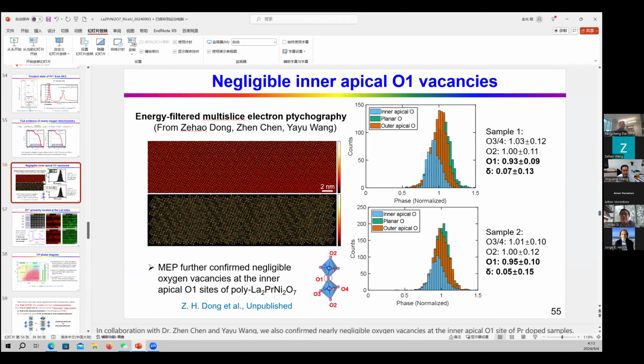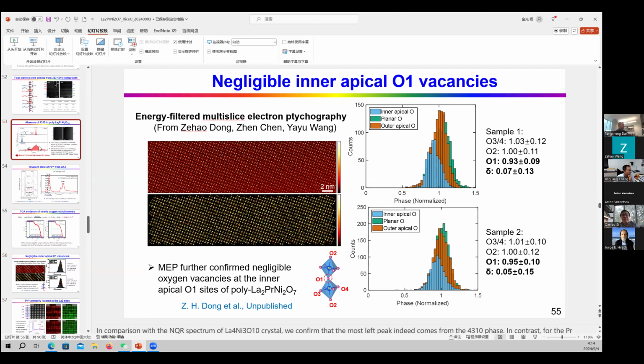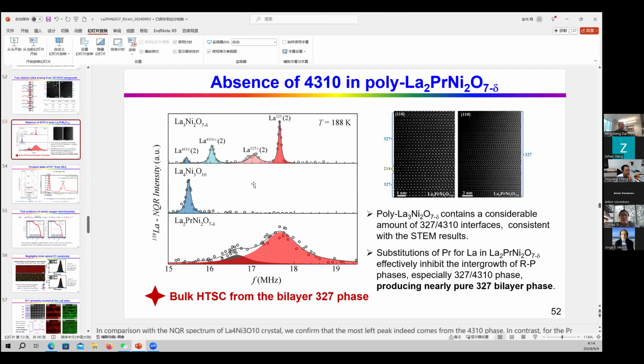So there are two factors. One is O1 site vacancy. There's almost no vacancy at the O1 site. And secondly, there's no intergrowth. I see. But for the undoped sample, there's a large portion of intergrowth, especially from the NQR measurement. Somehow the substitution of praseodymium can suppress the intergrowth, especially the trilayer phase. So then you think the intergrowth is not the reason for high Tc. It should be the pure phase. It's because we didn't observe this intergrowth for this doped sample.